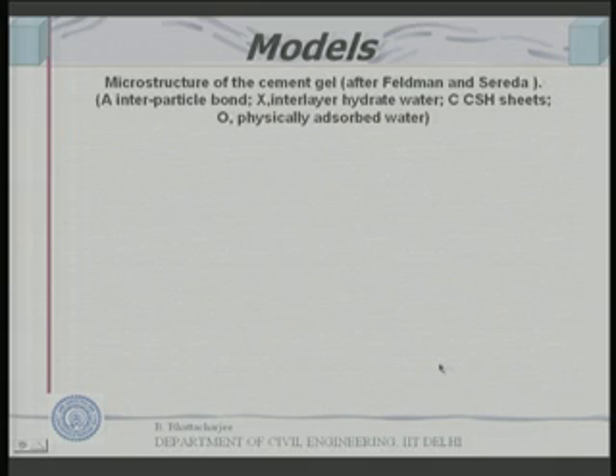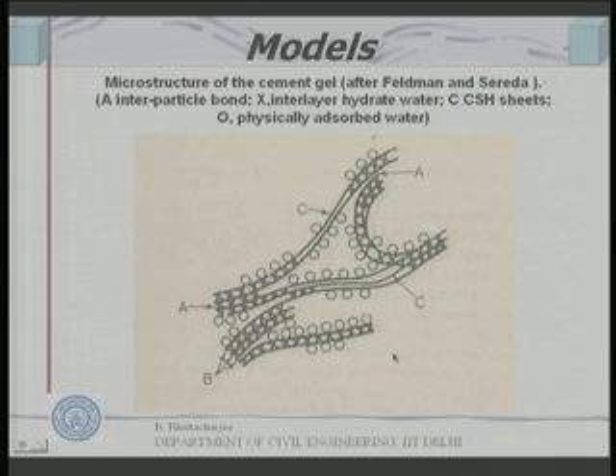Similar models were given by other people, like this one given by Feldman and Sereda, who define interparticle bonds, where different particles bond between them, then interlayer hydrated water defined by X, and then CSH sheets. So, this C stands for CSH sheets, these O are the physically adsorbed water, and in between you have X, which are the interlayer hydrated water between the layers. So, this is another model.